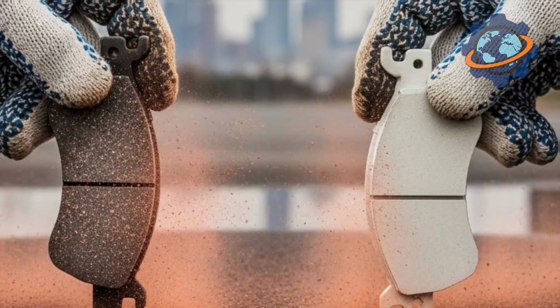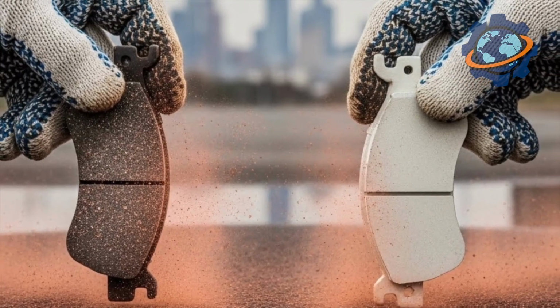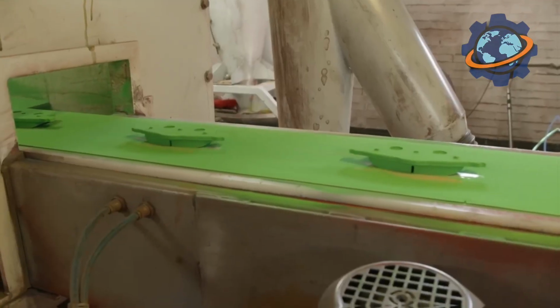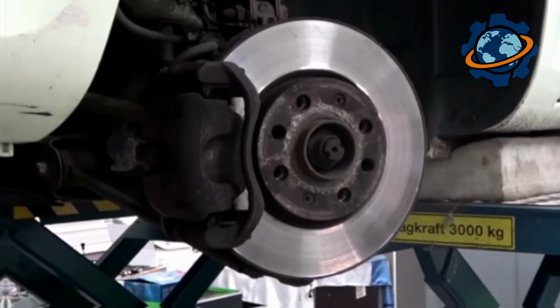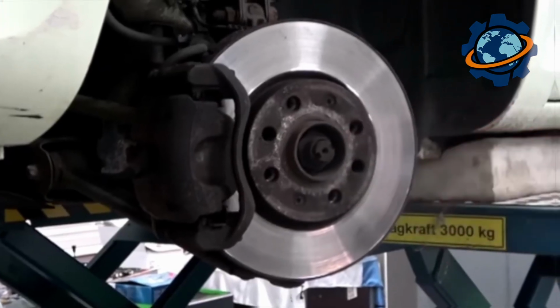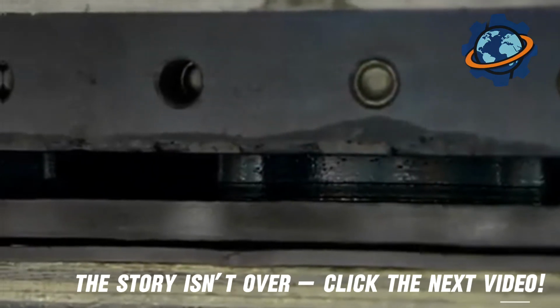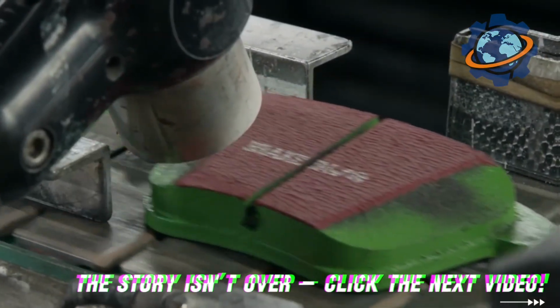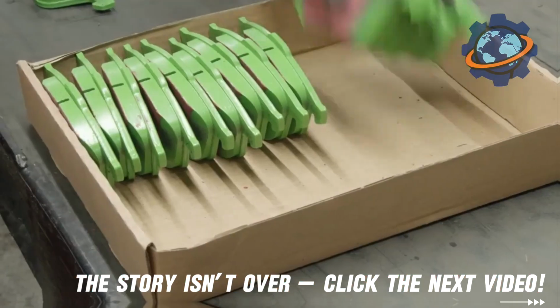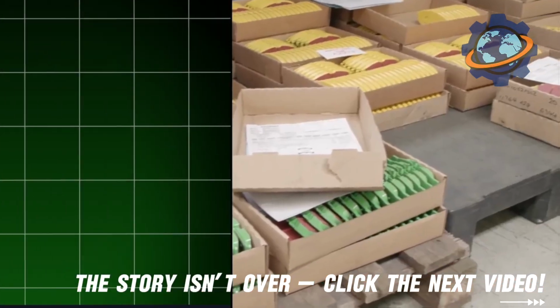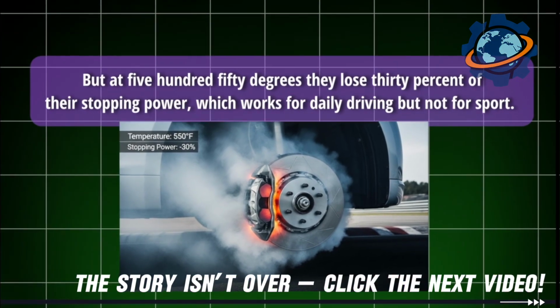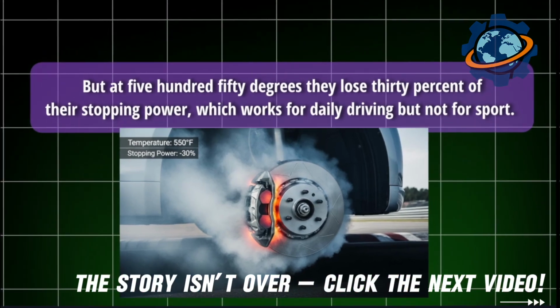Now, besides asbestos and metallic pads, there was an attempt to make organic ones. These are pads from the 2000s, the first mass replacement for asbestos. The base is synthetic rubber, fiberglass for reinforcement, Kevlar or aramid fibers for strength, plus barium sulfate and graphite. The soft compound gave a quiet bite, little dust, didn't scratch rotors. But at 550 degrees, they lose 30% of their stopping power, which works for daily driving but not for sport.